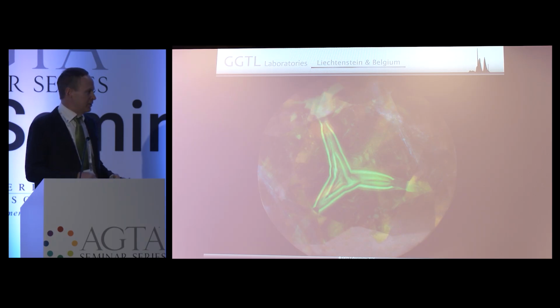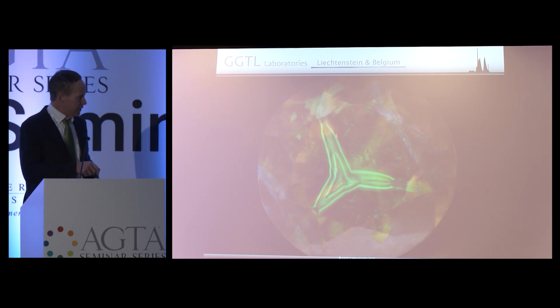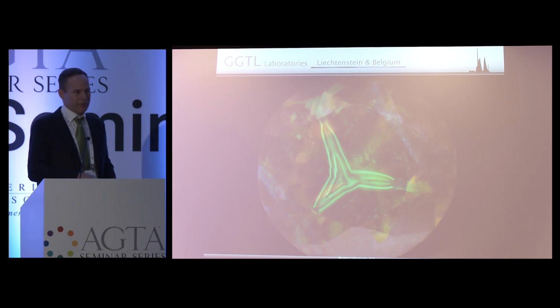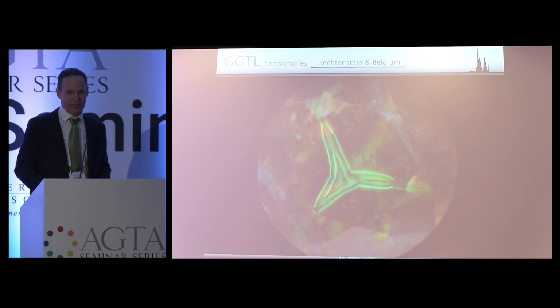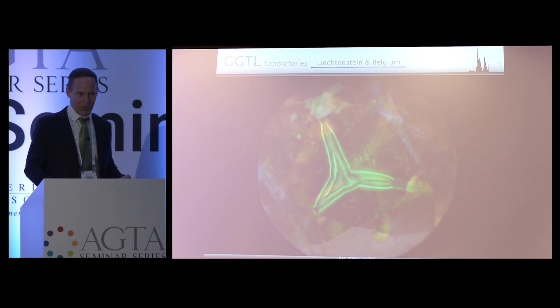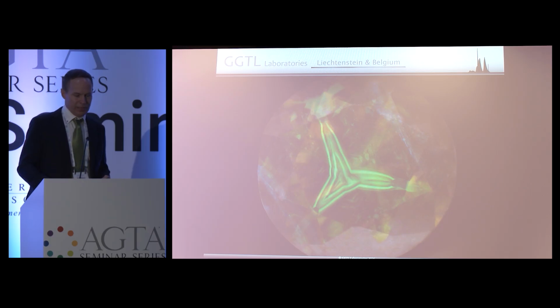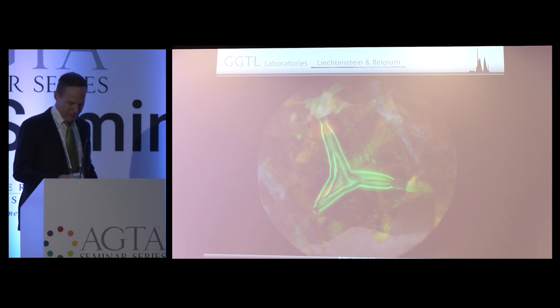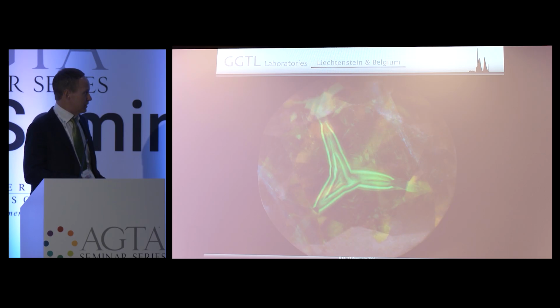So the growth again here is cuboid octahedral. That's why we see these features. And these features, especially this development of these reentrant faces here, are because most of those crystals, when you see a crystal of this material, oftentimes they don't form regular octahedra. They form stones that look like hopper crystals. If you know how salt looks when it crystallizes, they look like hopper crystals of salt. But it's not a hopper growth. It's just a mixed growth with reentrant faces. So you have certain faces that grow faster than the edges, and that gives you this interesting appearance of these stones and gives you this interesting fluorescence as well.